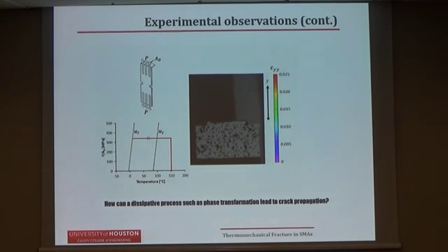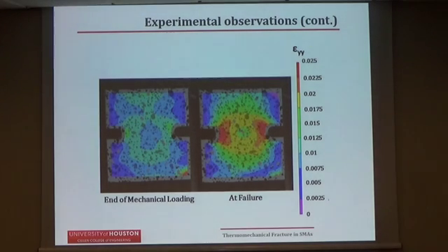We had a couple of ideas. One was that as the material transforms from the cubic B2 austenitic phase that has 12 slip systems to a monoclinic B19' crystal structure, that of martensite, that has only one slip system and 11 deformation twinning systems, it may be possible that since the yield strength increases, it becomes favorable to create new surfaces rather than move the dislocations around.